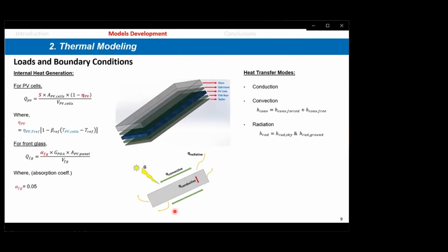Now, first, for the thermal modeling, the loads and boundary conditions. In this, we calculate the internal heat for PV cells by using this relationship here. This is the internal heat generation. S is the incident PV cell irradiance. A is the area of the cells, and V is the volume of the cells, and eta, the important factor here, is the efficiency, which is taken to vary with temperature. It will decrease with temperature according to this linear relationship for polysilicon based